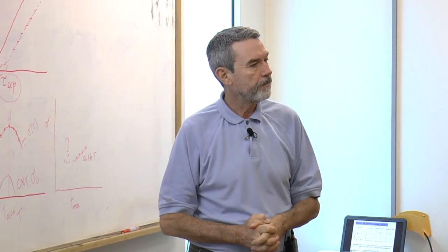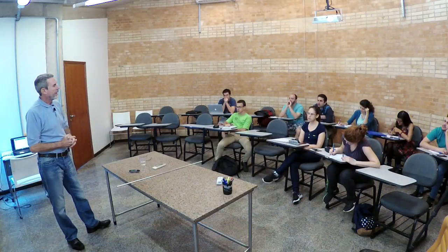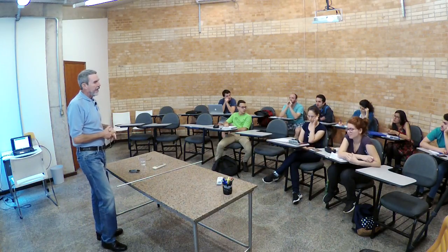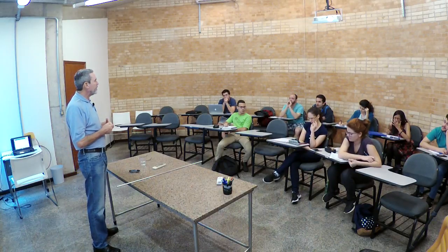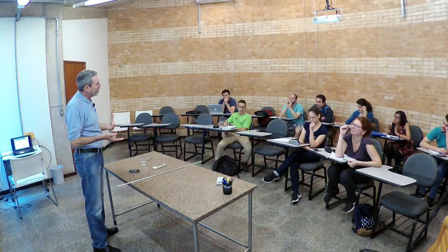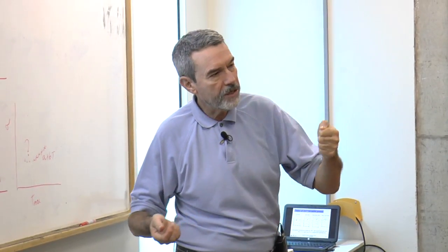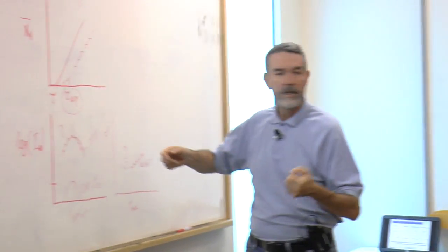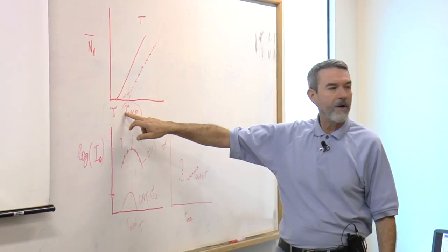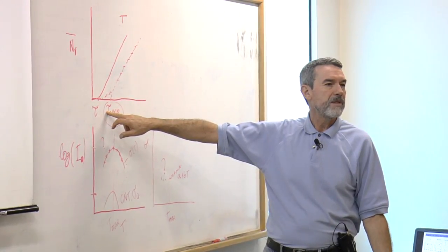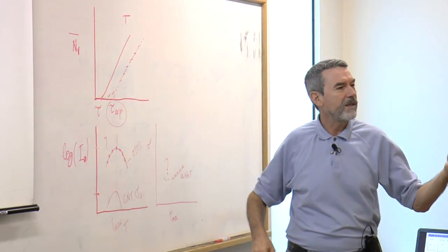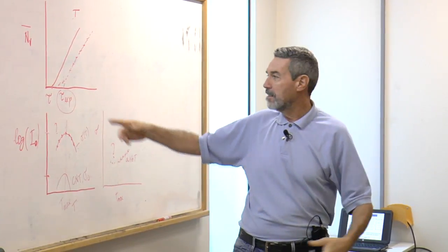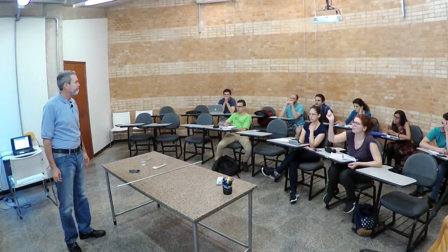Any questions? Excuse me, before Tmax, relaxation doesn't play a role? It relaxes much faster than the time of nucleation. If you compare the relaxation times with tau, the relaxation times are 2 orders of magnitude faster. So the liquid relaxes even before the system starts to nucleate.